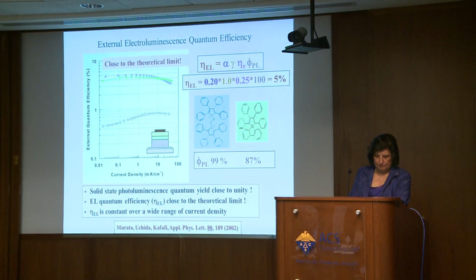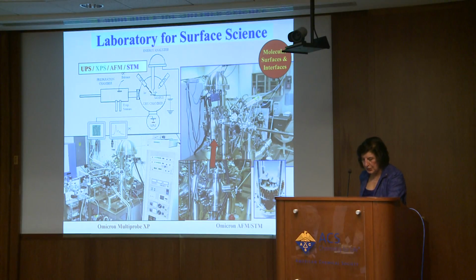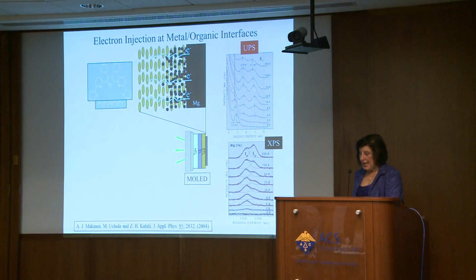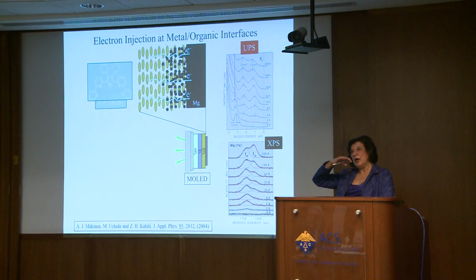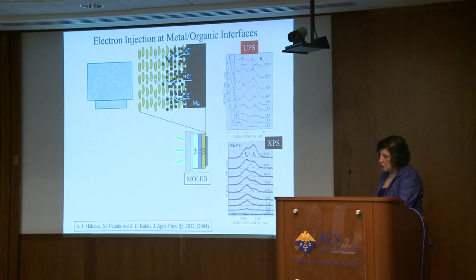fluorescent material. We also wanted to learn about the role that interfaces play in these materials, so we decided to do some ultraviolet photoemission spectroscopy. And we found that depositing a metal on an organic surface gives rise to an interface very different from depositing an organic on a metal surface. We show here the interface between magnesium, which is used, as I showed you, as a cathode, where we are depositing it on the organic